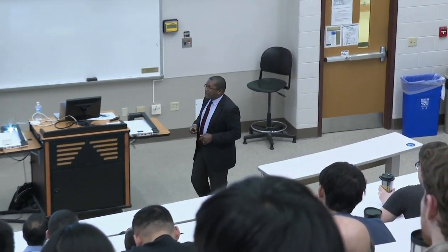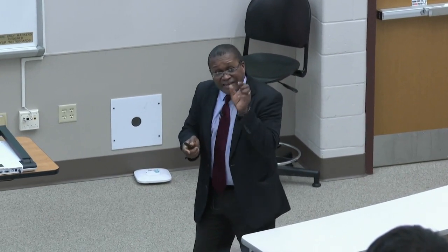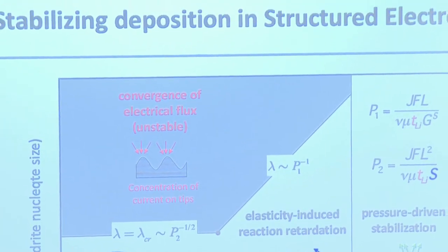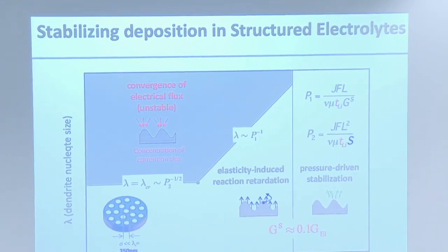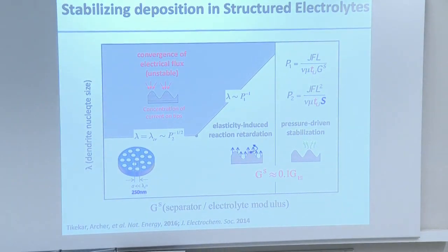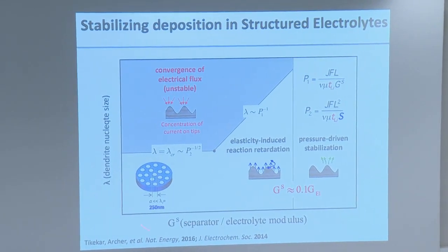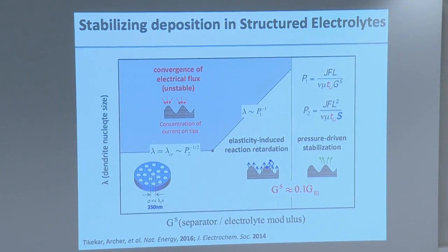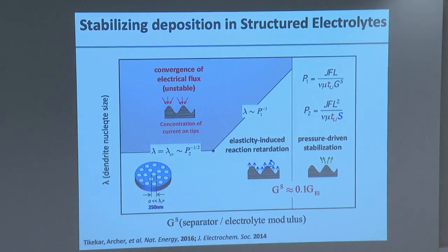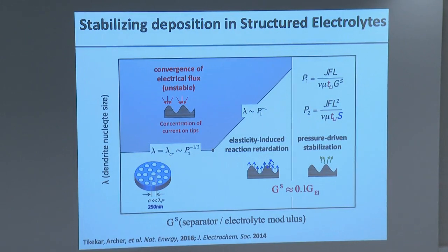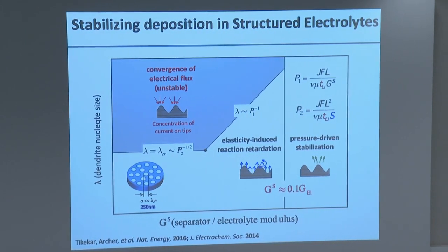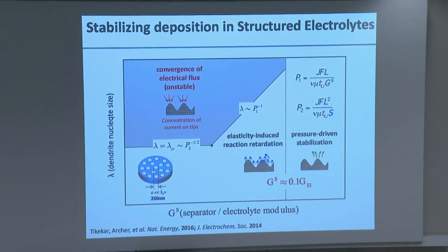We're saying that if you design the system right, in such a way that lambda, the length scale of the bumps, is smaller than a certain critical value, any modulus should be able to stop the dendrites from growing. Controversial, the stuff that you should be thrown out of a room like this for saying. But we said it, and then we did it, right? So the question was, how in the world can you do this? Well, you can predict what that length scale needs to be by looking at the normal parameters in a typical electrolyte. It turns out for a typical one molar LiPF6 EC/DMC popular electrolyte, that number is 250 nanometers. So if you can keep those bumps below 250 nanometers, you can stop dendrites from growing in any electrolyte.